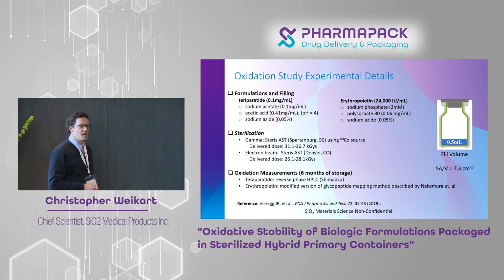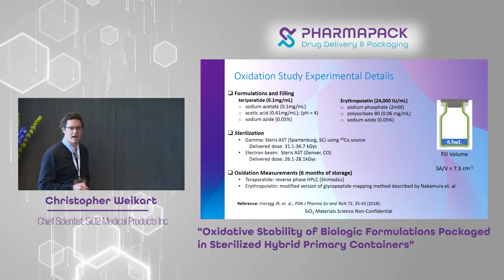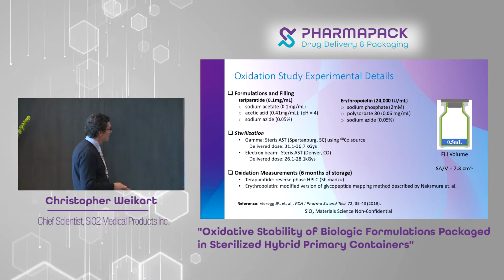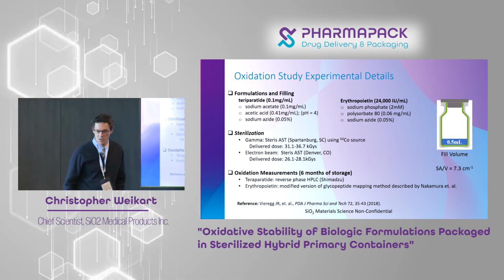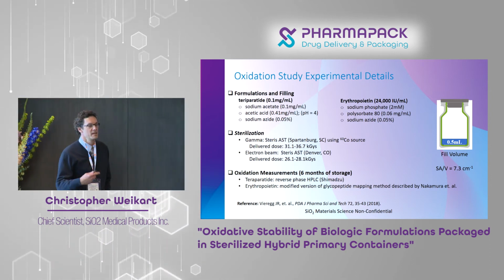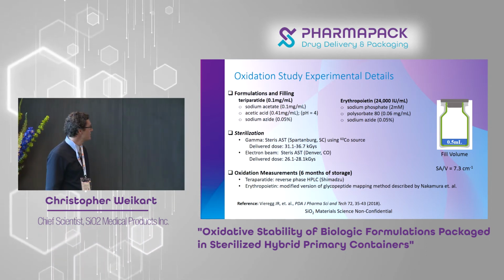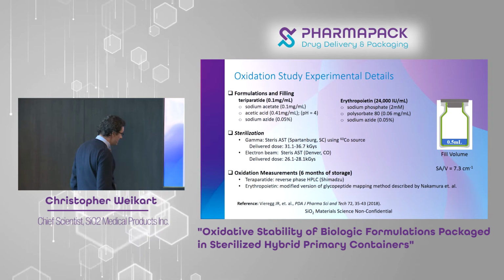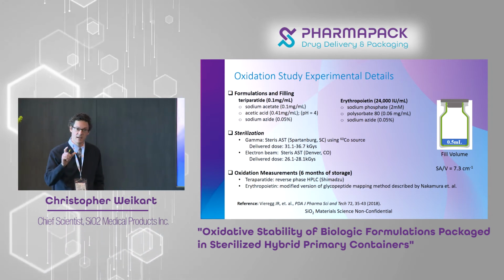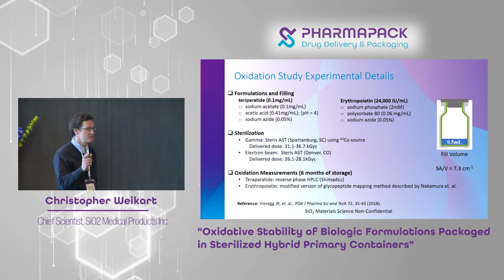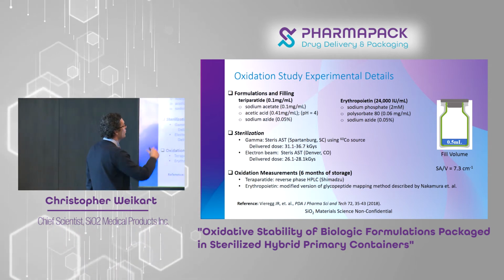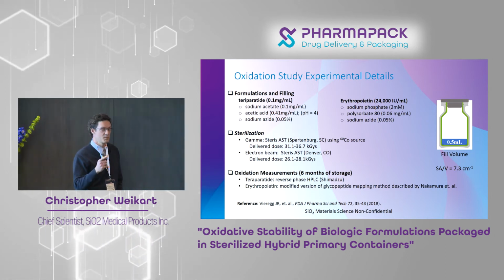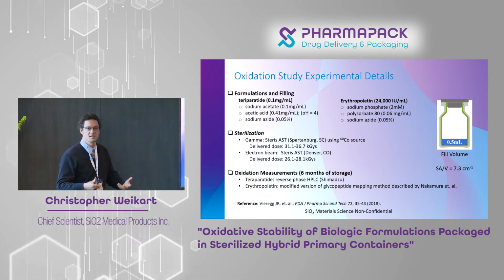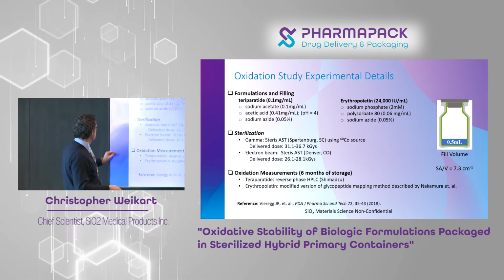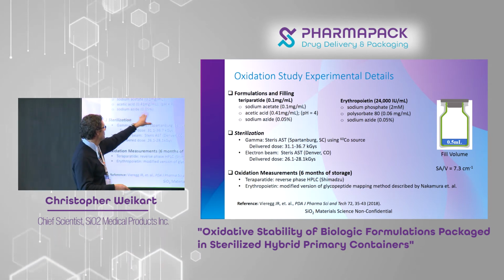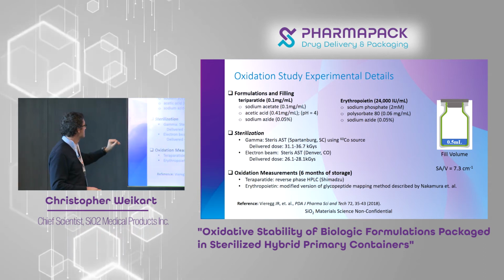So just to set up those experiments, we ran a study at the University of Chicago in the US. And we looked at 2 different drug formulations. We chose these in particular because they're, in general, considered more oxidatively unstable than most other drugs. Teriparatide is a peptide. It has 2 methionine amino acids in its backbone that make it susceptible to oxidation. So very good candidate. And then erythropoietin has an amino acid that also is oxidatively unstable within its interior, but it's still accessible. It can still be oxidized. And normally you would find an antioxidant in the formulation. We took that out just so we're looking at the drugs by themselves.